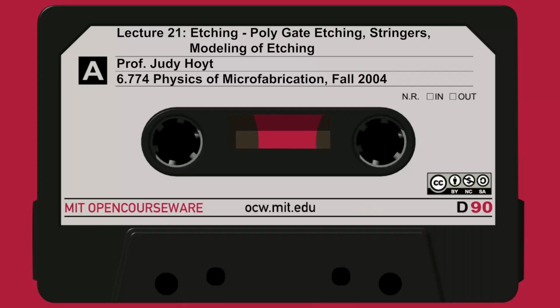Okay, so the next step is step number 2. You're clamping the wafer mechanically to the chuck to get good control of the temperature, and you have certain characteristics in that step. So that lasts about 20 seconds. The next, step 3, is the first etch. Remember we mentioned when you're using a gas that's highly selective, you need to first start out with a breakthrough etch to get through the native oxide. Here you're etching for about 10 seconds, and you etch just based on time. You're flowing C2F6, I guess that's the only thing you're flowing, and you've got RF power on the top and bottom of 250 and 40 watts, and your pressure is 13 millitorr. So this should break through any native oxide for about 10 seconds.